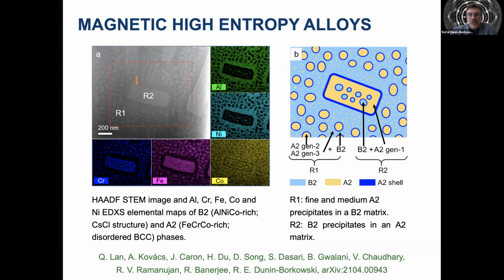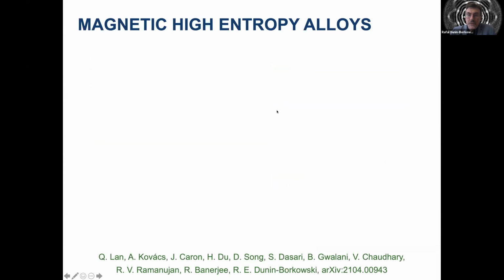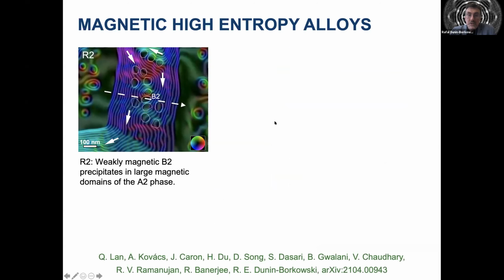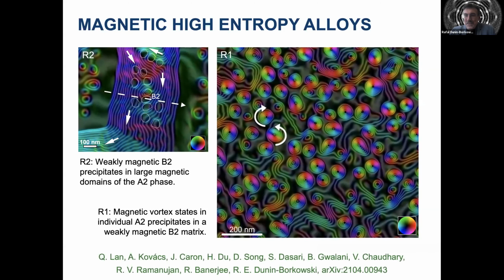And the reason that the magnetic properties are so complicated becomes apparent when we image the magnetic microstructure with off-axis electron holography, because whereas the R2 region, which contains the strongly magnetic phase with the weakly magnetic void-like regions inside it, shows large magnetic domains that are relatively simple, in the region outside it, the region which is labeled R1, which contains lots of little precipitates, in fact, the holography reveals that every one of these little precipitates contains a magnetic vortex where the magnetization spins either clockwise or counterclockwise. And when these precipitates are imaged in the presence of an applied magnetic field, then every one of the precipitates reverses magnetically at a different value of the externally applied field.